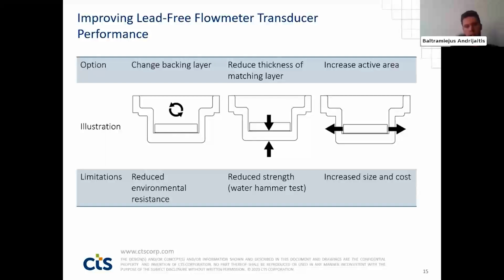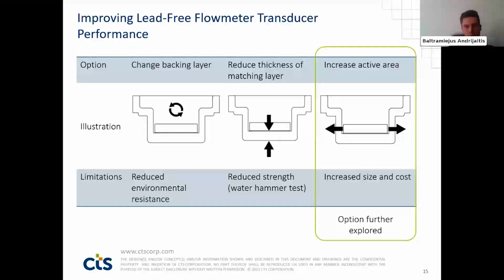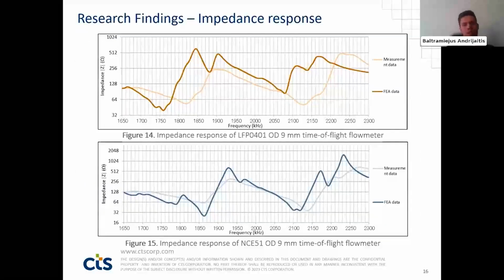And finally, increasing the active layer area. However, it would increase the size of the transducer, the whole assembly, and also the pricing. So for further investigation, we chose to increase the active layer area from the used outer diameter 7 to outer diameter 9. And further, the same process of assemblies, measurements, and finite element analysis was performed to get the investigated changes. More graphs. On the lead-free graphs, we can notice lower overall impedance values.